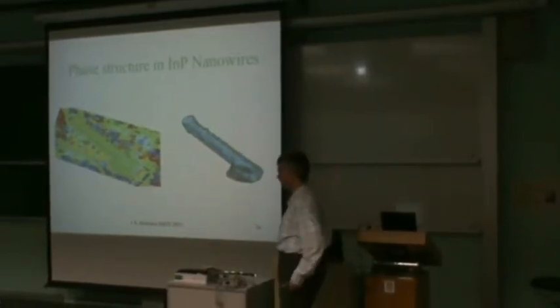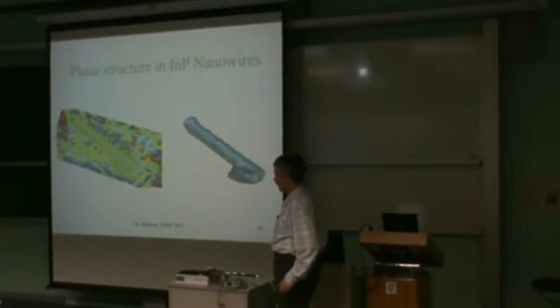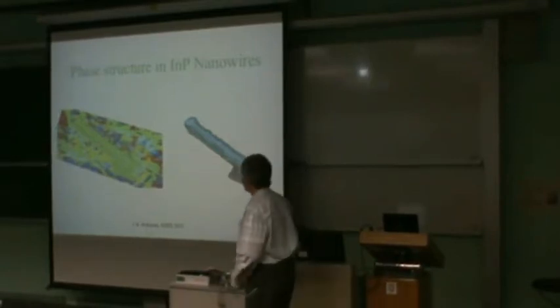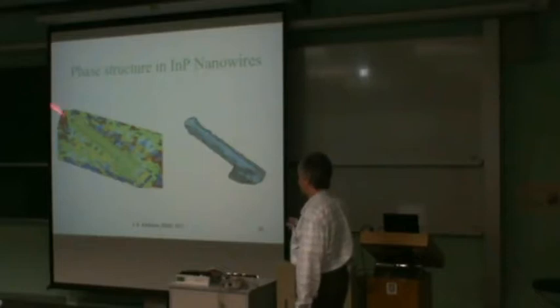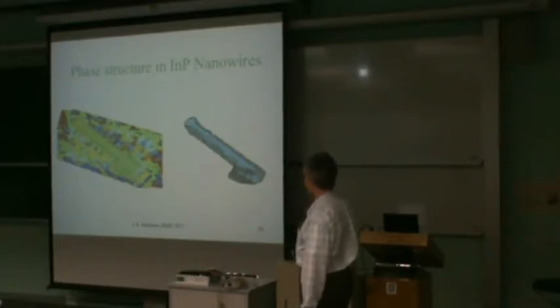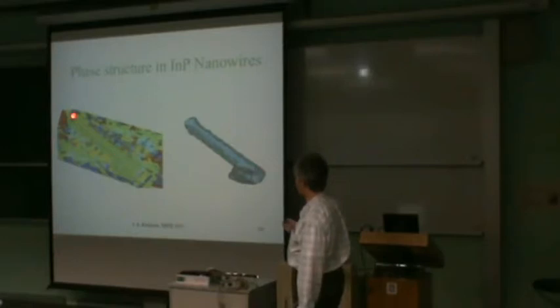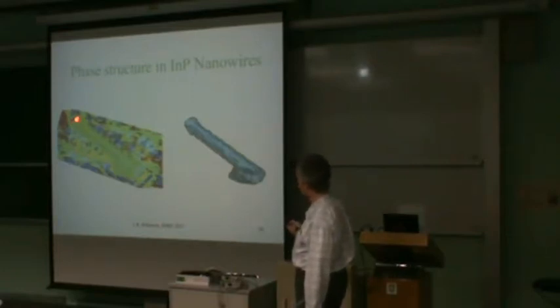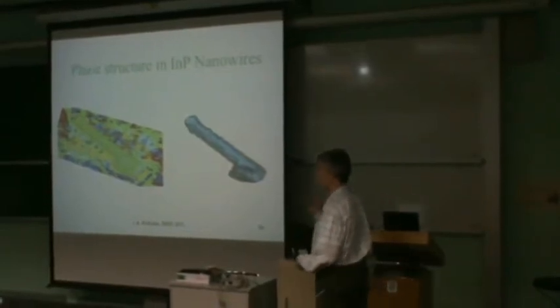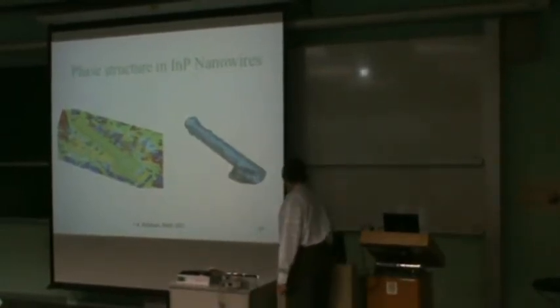Can you tell the magnitude of the gradient? Is it more strain-free towards the free edge? We haven't really. It's really at the level of visibility. So I'm not going to really stress the point, but just my eye says that there is a little bit more gradient going out in that direction. This, by the way, we know from the SEM picture, is not the end of the wire. This is just a missing piece of wire. So there is probably a stacking fault at this position, and there's more wire beyond it, but we don't see that because we're looking at just one bright piece of that wire.